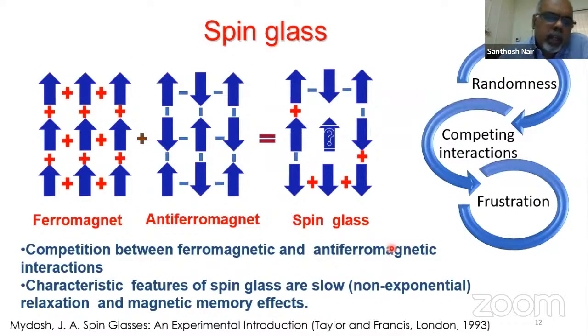Now, when you have a system with the presence of ferromagnetic and antiferromagnetic interactions, you can end up with a glassy phase due to frustration, etc. The competition between ferromagnetic and antiferromagnetic interactions has characteristic features: spin glass behavior, slow relaxation and magnetic memory effects. So we can expect something like that when you have a competition. In our system, neutron says there's no long-range ferromagnetic ordering, nor long-range antiferromagnetic ordering. But in the magnetization data, M versus T, you see a signature of some ferromagnetism. The Curie-Weiss fit also suggests that.